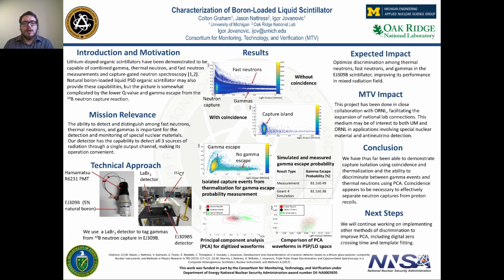Additionally, to demonstrate our ability to perform capture-gated neutron spectroscopy, we performed a measurement where we looked at events which were preceded by proton recoils, and you can see once again we were able to isolate the capture island, as well as able to isolate the band of events which correspond to capture events with some energy deposition in the boron-loaded liquid scintillator by the lithium de-excitation photon.